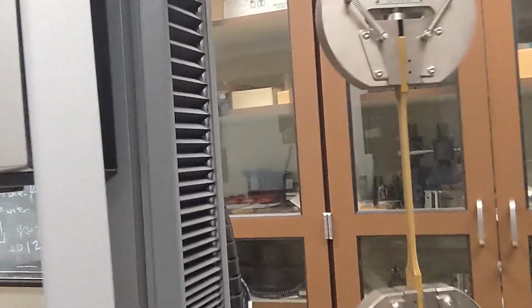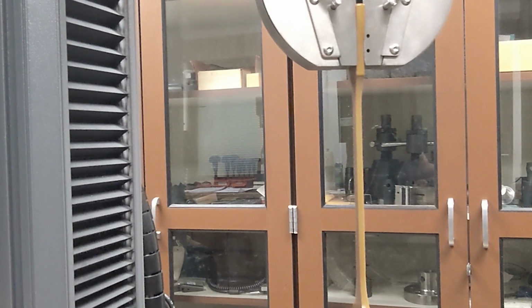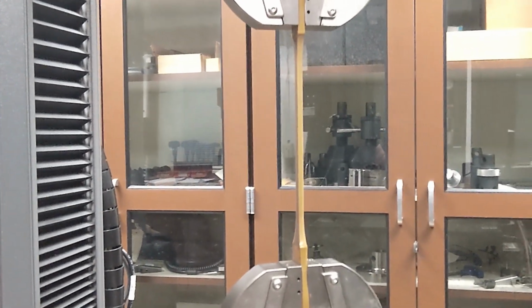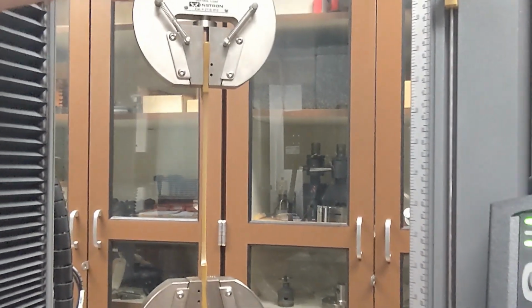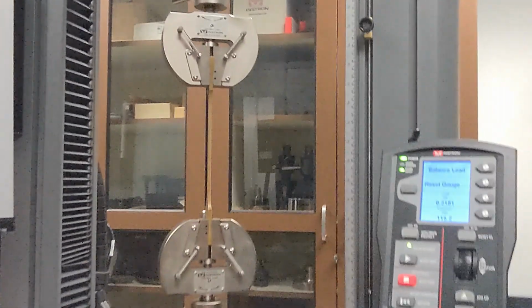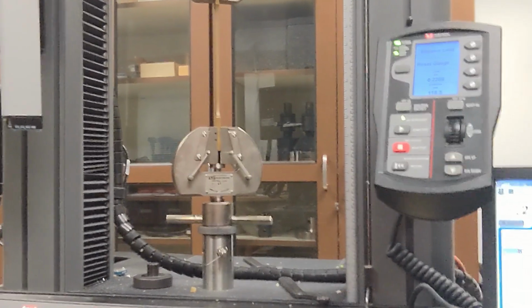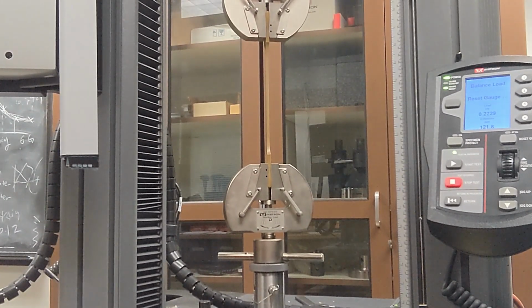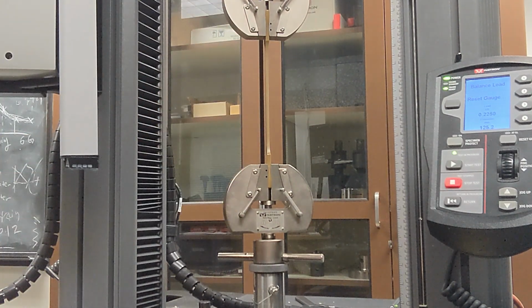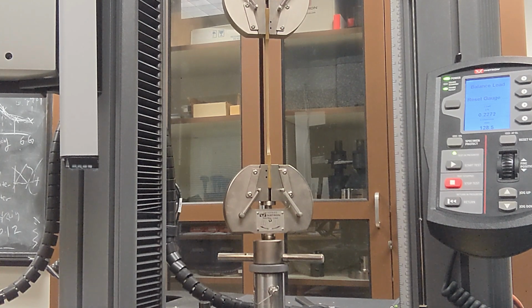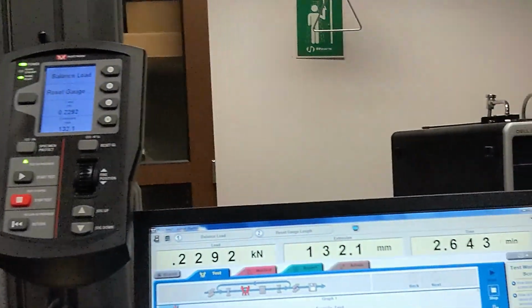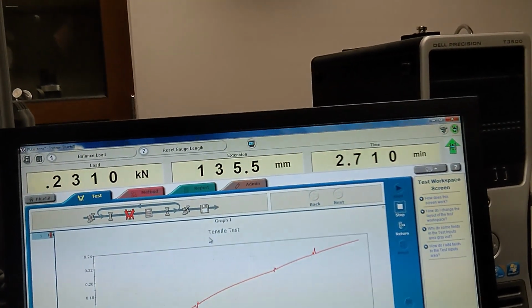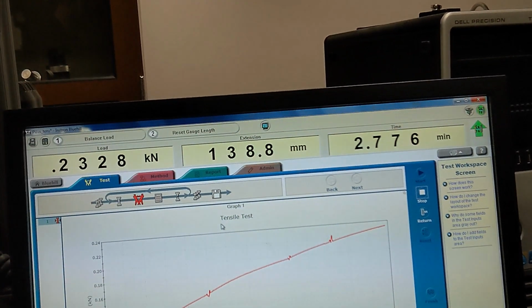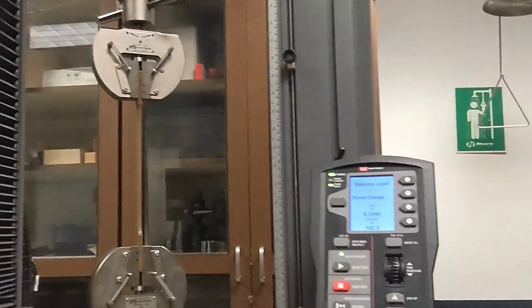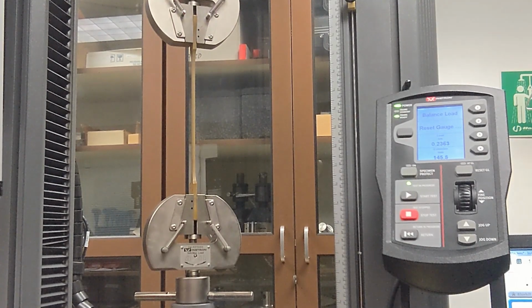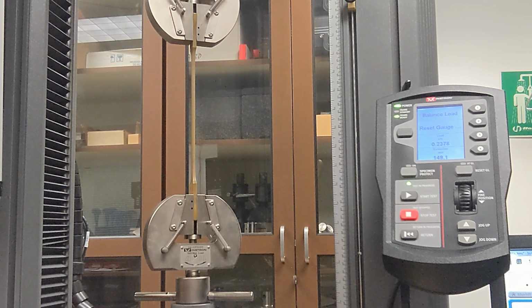A closer look, you can see it's really stretchy. So our amorphous chains are becoming elongated and stretched out, but we haven't reached where the cross links are stopping tension, plastic deformation from happening. We're still elastic. And our forces, if you want to look, you're all the way up to 0.23 kilonewtons and 140 millimeters of extension. So already much greater than our LDPE. Not quite at HDPE at 50 millimeters per minute. That was around 200.